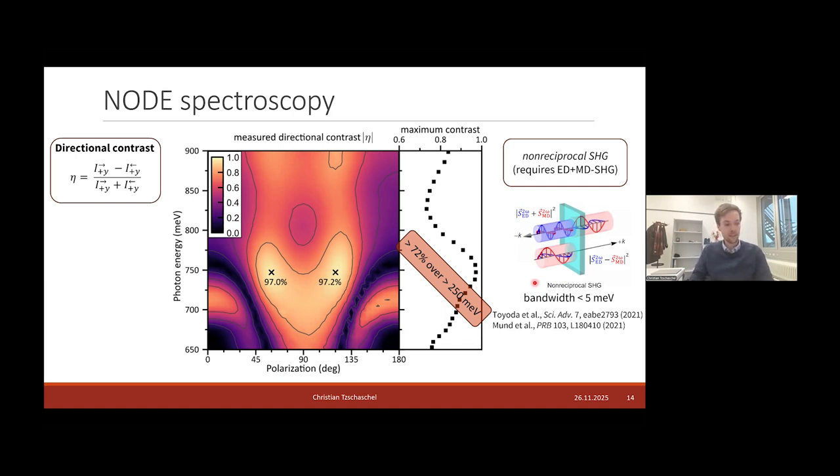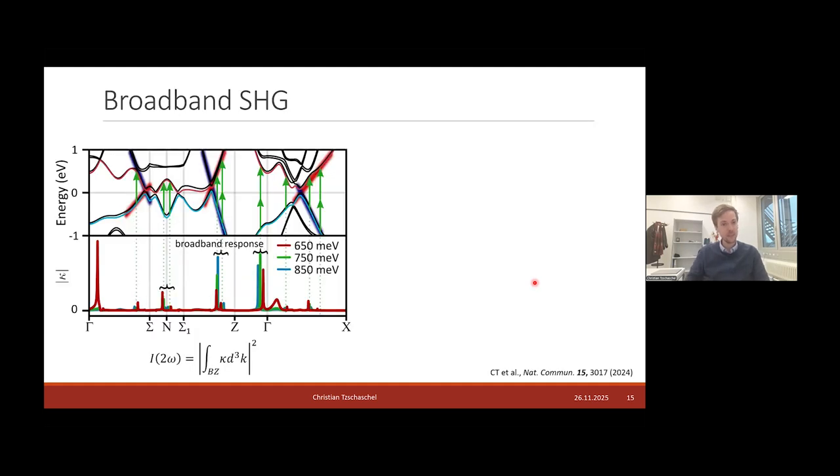To understand better why this is the case, we then got in touch with some theory collaborators who calculated the electronic band structure of the material. In the band structure, they indeed find that there are Weyl nodes in the material. Now, if you show the band structure along this path between high symmetry points, you typically miss the Weyl points. So this path is not expected to go through the Weyl points. That's why the rough locations where Weyl points would be are only shaded here.